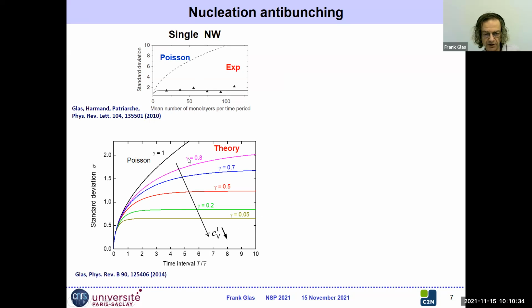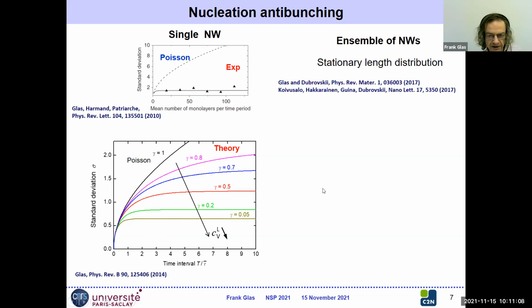And all these curves depend on various values of this gamma parameter, which is the key parameter of the theory. This gamma is simply the ratio of the nucleation probabilities after and before the formation of one monolayer. In the case of the Poisson distribution, there is no correlation. So it's the only case where gamma equals 1. But in all cases with nucleation anti-bunching, gamma is less than 1. And the smaller gamma is, the lower is the plateau at which this standard deviation saturates. This has also positive consequences for ensembles of nanowires, which I'm not going to discuss today.